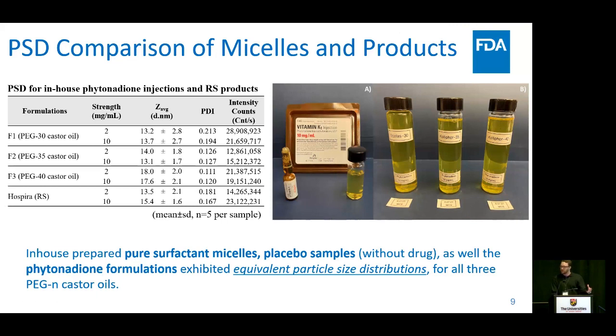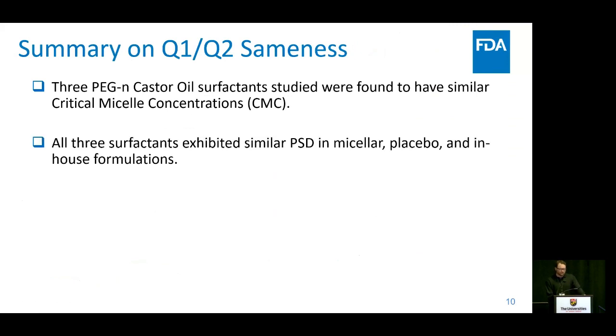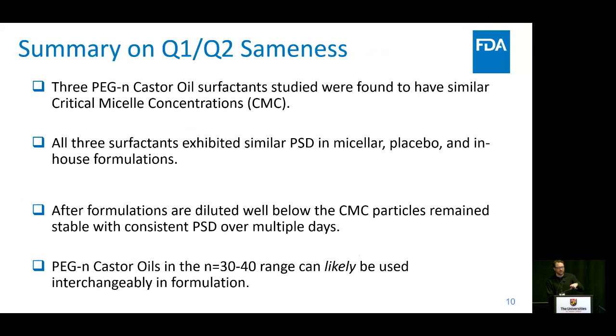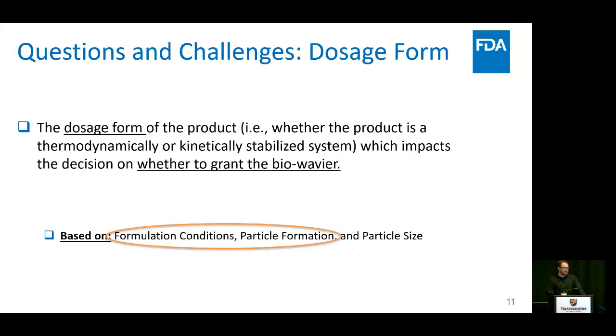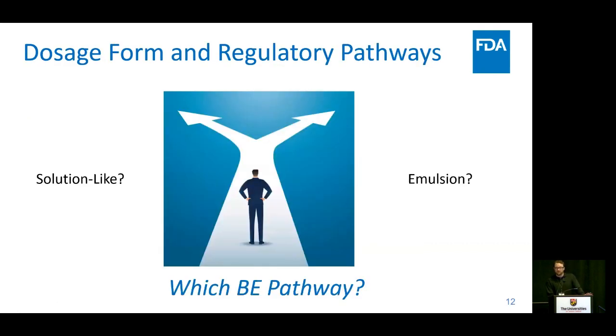This goes into the second question for this product, which is, what is the true dosage form here? I know we had an aqueous colloidal solution and an injectable emulsion, and these have slightly different terminologies and cases for them. The important thing again is that those two things are distinctly different, because one is a thermodynamically stable system and one is a kinetically stable system. This is evaluated based on the formulation conditions, the type of particles that are formed, and that particle formation. That's important because the risk associated with solution-like products versus, say, an emulsion are slightly different, where an emulsion has all of its physicochemical properties also closely related to the manufacturing process.